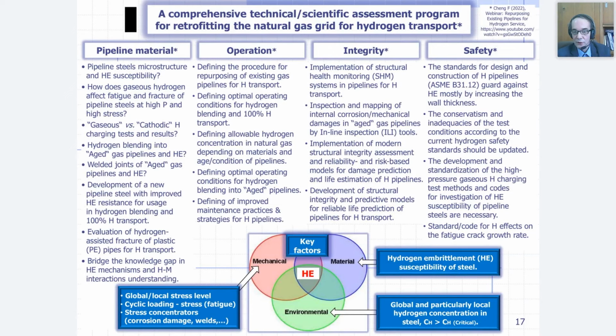So we also need to develop standardized high pressure gaseous hydrogen charging test methods for experimental investigation of hydrogen susceptibility of pipeline steel. In Europe, there is not a lot of equipment for high pressure hydrogen testing. Contrary to that, in the United States of America, there are a lot of efforts led by Sandia National Laboratory and the United States energy governmental sector regarding the experiments with high pressure gaseous hydrogenation of material in order to investigate the hydrogen embrittlement susceptibility of particular pipeline steel.